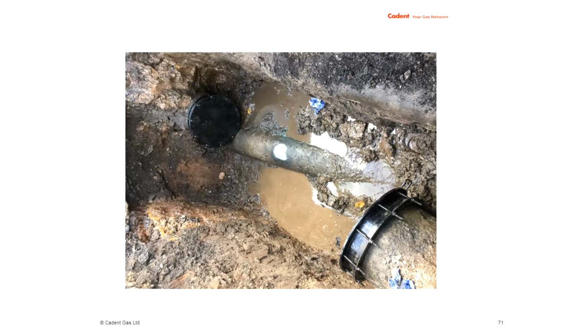And that there is where we've removed an old medium pressure pipeline that was in contact with an intermediate pressure pipeline. And you can see the markers left in the middle of the pipe there, where it was in contact and causing a drain on the cathodic protection.